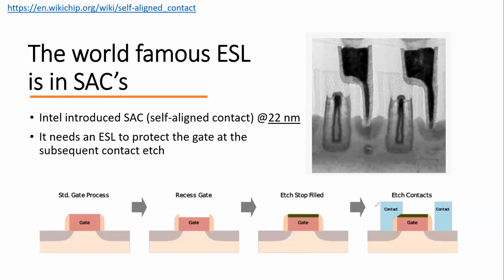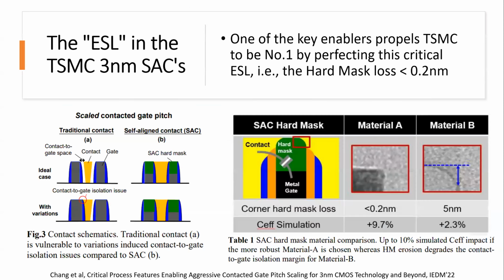You put something to stop it, and that is your stop layer right here. It's one of the most famous ones in the world right now. It's one of the most difficult ones. Okay, and last year TSMC published a paper on this subject. All right, so the TSMC 3 nanometer self-aligned contact, and this is the one I would say is the key enabler that propelled TSMC to be number one, by perfecting this critical stop layer, which they call a hard mask. It's something to stop upon. So it can be a hard mask, doesn't matter. You look at the etch loss. So he's talking about how fine the control should be in order to make things work.